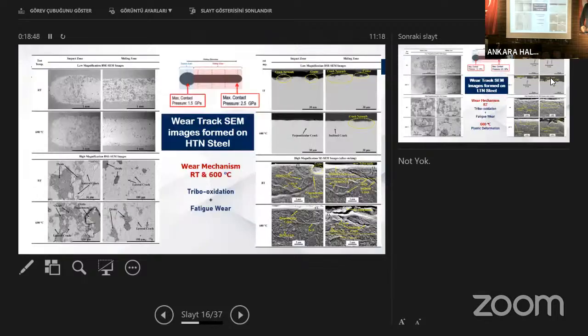I am skipping some of the scientific details. After the test, those are the testing conditions. The contact pressure at the point of the impact zone was 1.5 gigapascal, and in the sliding zone, the contact pressure is increased to 2.5 gigapascal. Very large contact pressure. So we examined the surface.